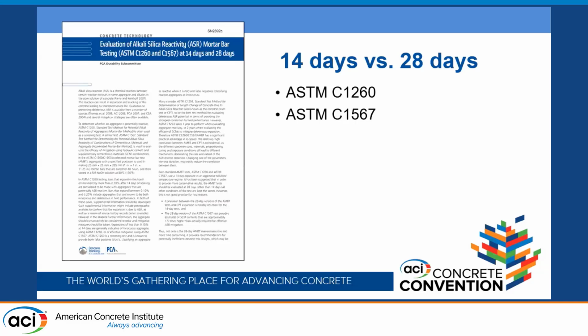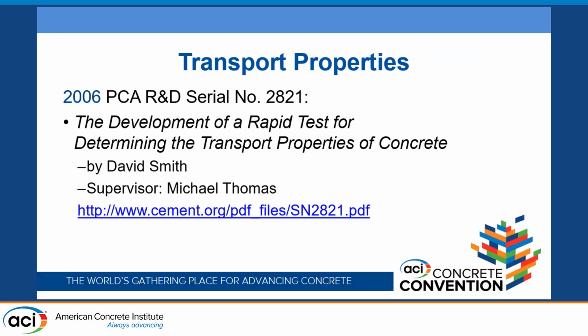versus 28 days. One thing that does happen in our industry is if we think one thing's bad, well, what happens if we make it longer? Is that worse? What this research showed is that extending the duration of the test for a length such as 28 days is overly conservative, and it results in estimates of much higher levels of SCMs being needed to control the expansion than is actually required in concrete for ASR mitigation. And furthermore, the minimum level of SCMs required to control expansion during the 14-day limit was in good agreement with the amount of SCMs that are required. So we took this information, very important to us, and the PCA's Product Standards and Durability Subcommittee developed a white paper based on this research for communications with Department of Transportation entities and other specifying agencies.